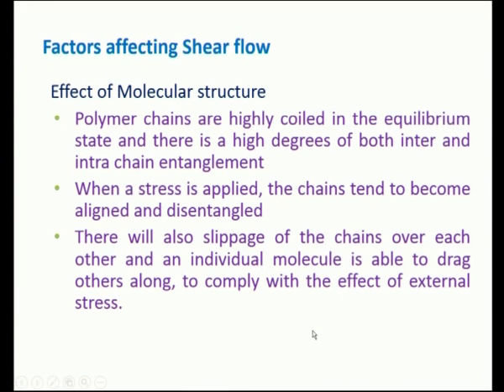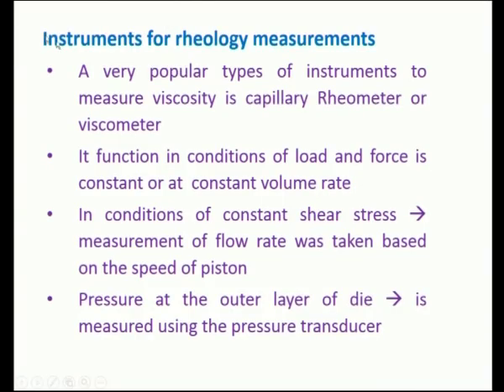Now the instruments for rheology measurements. A very popular type of instrument to measure viscosity is the capillary rheometer or viscometer. Its function is under conditions of constant load and force, or at constant volume rate. In conditions of constant shear stress, measurement of flow rate was taken based on the speed of the piston. Pressure at the outer layer of the die is measured using the pressure transducer. This is one way to measure viscosity.